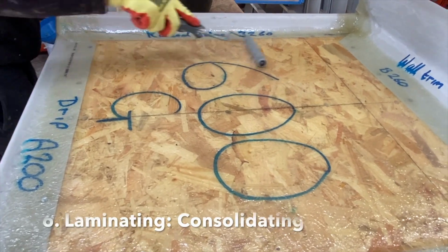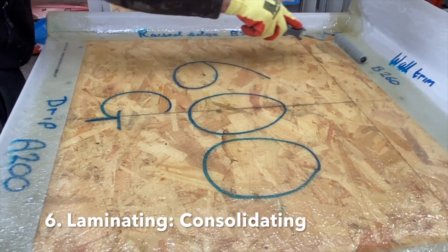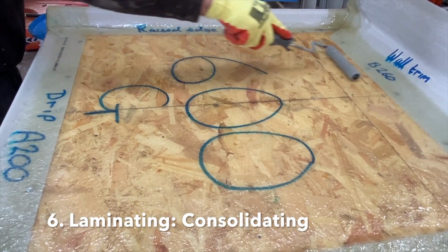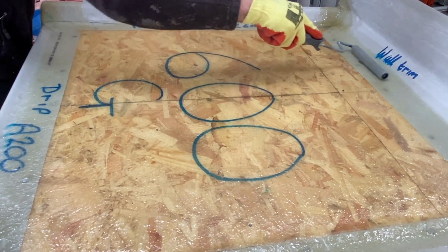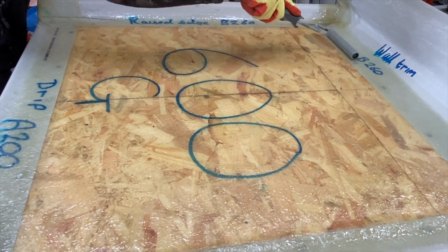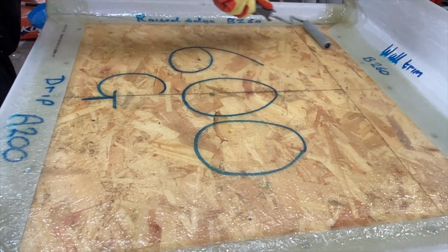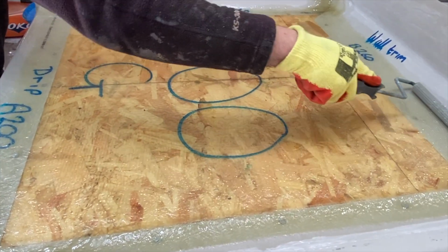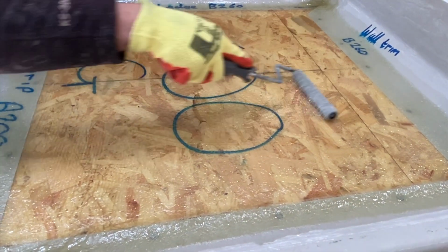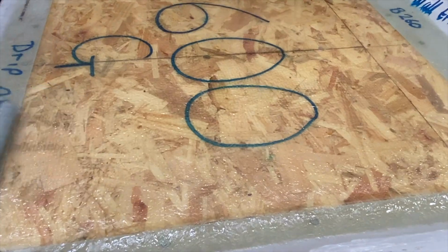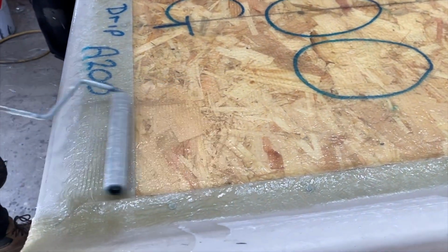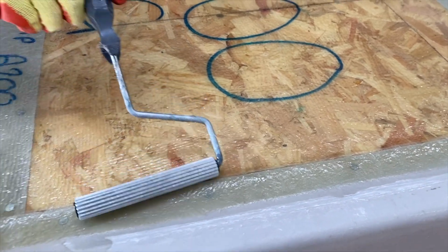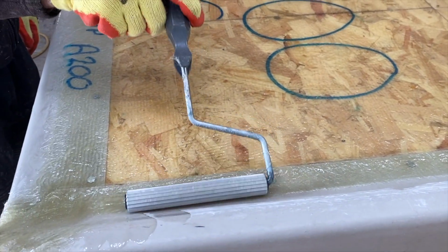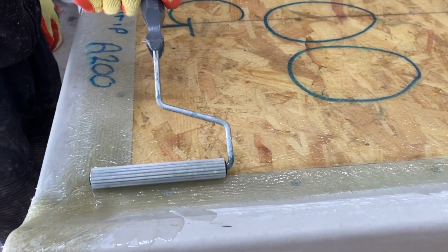Once the laminate's been adequately soaked in polyester resin, the next thing to do is to consolidate the laminate using a paddle roller. This is a metal cylinder with grooves and it's designed to drive resin into the glass fibre matting and force out any air bubbles. This is a critical step in achieving a uniform, seamless and consistent laminate.